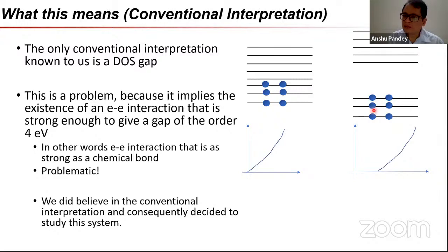It would seem that we are in this regime where we have a gap in the density of states spectrum all the way till 4 eV. So this is a big problem, because this implies that in gold silver we have an electron-electron interaction. We don't care right now whether it's superconductivity or what it is, but there's an electron-electron interaction which is strong enough to give a gap in the spectrum, which is of the order of 4 eV.